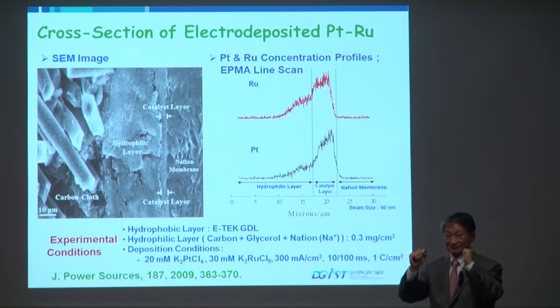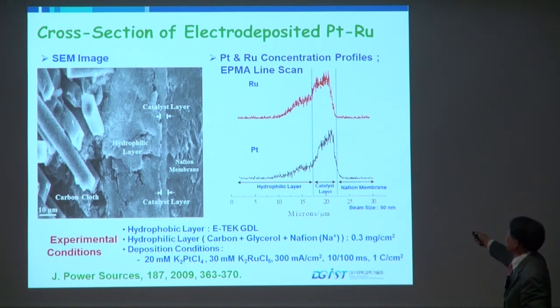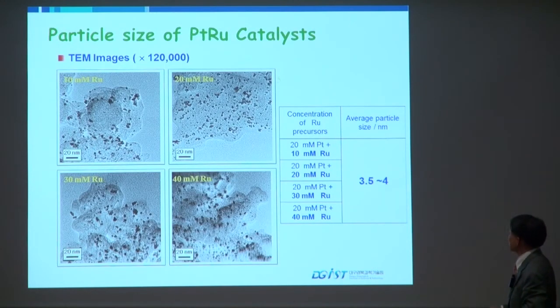Okay? So we checked the cross section of this catalyst layer, and it turned out to be a ruthenium pair, platinum pair. So they are in a very good parallel fashion. So we do have a co-deposition of these, and the particle size at different concentration ratios of platinum and ruthenium is about 3.5 to 4 nanometers. So that's a suitable, good size of particles at different morphologies.